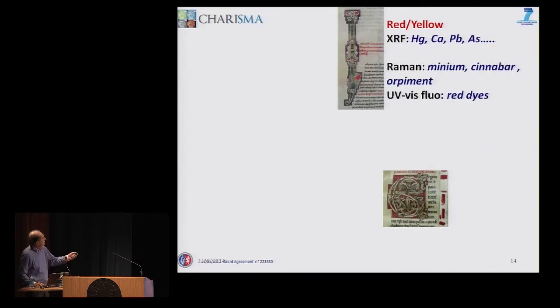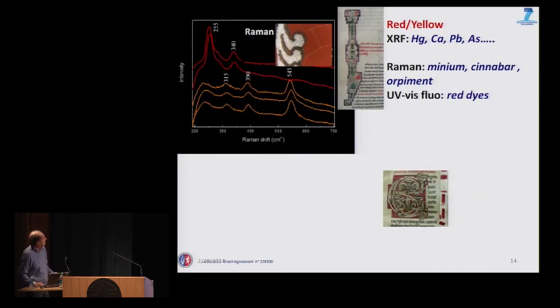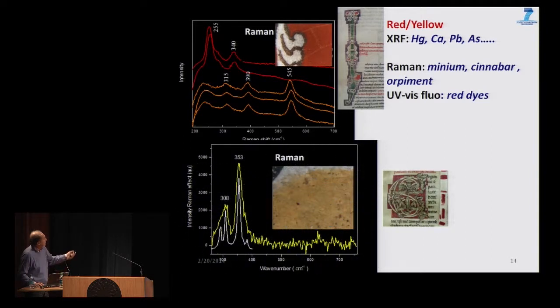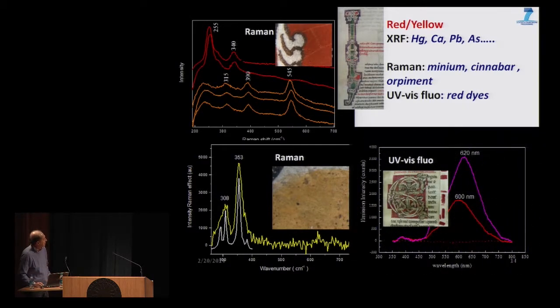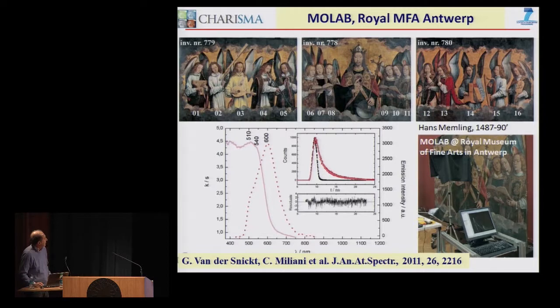Or in this case, for yellow and red tones, mercury and lead were detected, as confirmed by Raman, due to minium and cinnabar. The yellow, the arsenic, was due to orpiment, and red dyes were also detected using ultraviolet-visible fluorescence. And particularly advantageous was this system that was developed inside CHARISMA that is able to carry out measurements on